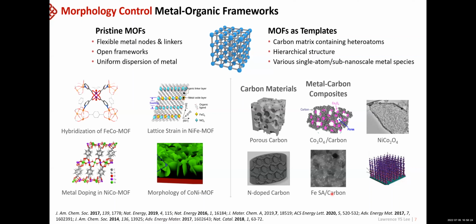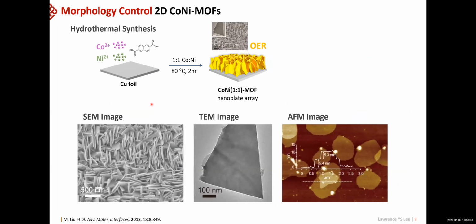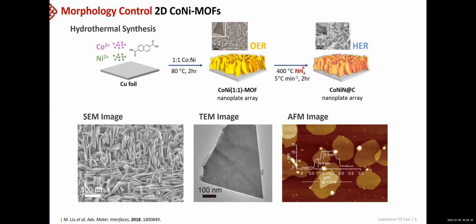In our case, we wanted to use a MOF as it is, as an electrocatalyst for OER. So what we did was we grew the MOF in a 2D structure, and we chose cobalt and nickel, which are located on opposite sides of the volcano plot. Then we tried to control their ratio and grow the 2D cobalt nickel MOFs. As you can see from the SEM and TEM images, we were able to grow a very thin, quite uniform nanosheet array of this cobalt nickel MOF, with a thickness of about 5.3 nanometers. We use them as an OER electrocatalyst, but we can also treat them at high temperature under ammonia and turn them into nitride species, which has shown good HER performance. But today I'm just going to focus on the MOF itself.